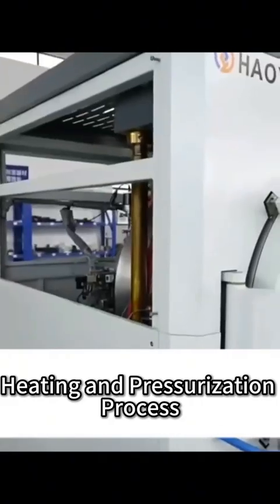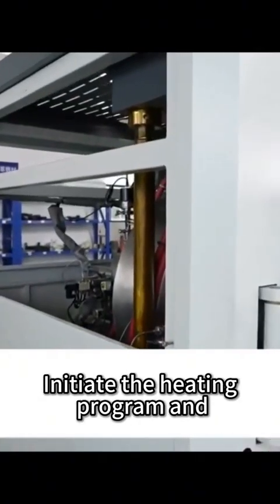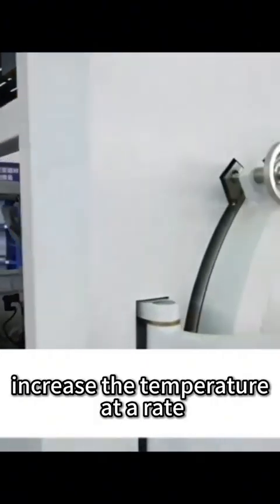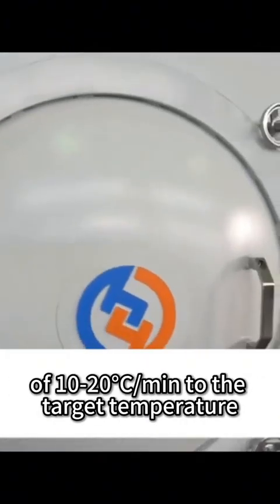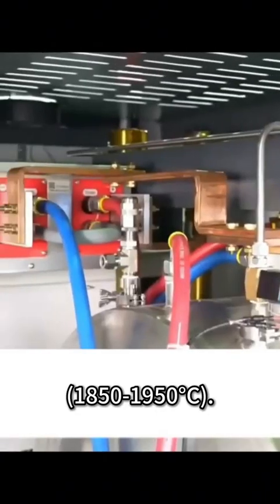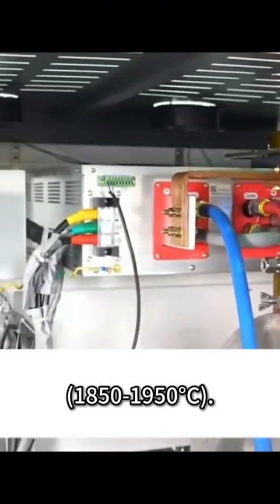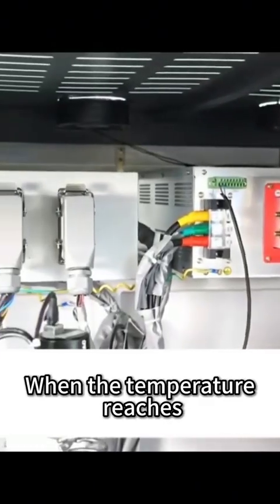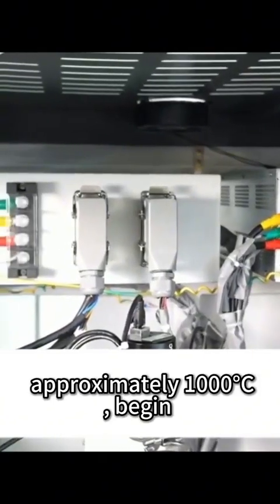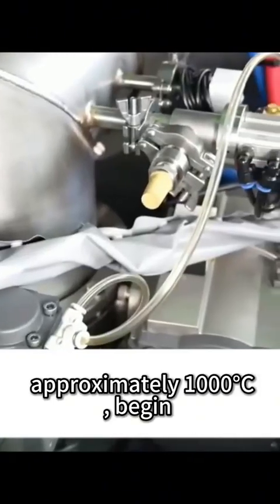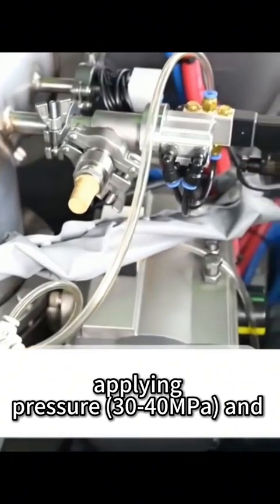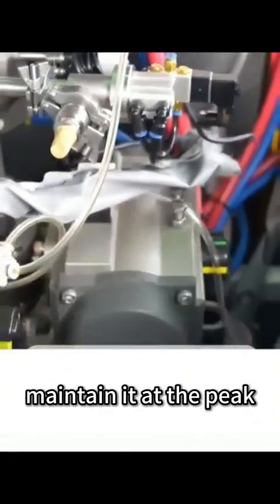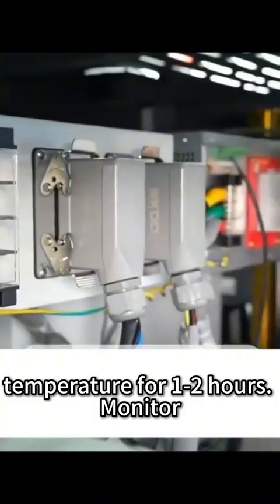Heating and pressurization process. Initiate the heating program and increase the temperature at a rate of 10-20 degrees Celsius per minute to the target temperature of 1850-1950 degrees Celsius. When the temperature reaches approximately 1000 degrees Celsius, begin applying pressure of 30-40 MPa and maintain it at peak temperature for 1-2 hours. Monitor the temperature and pressure curves.